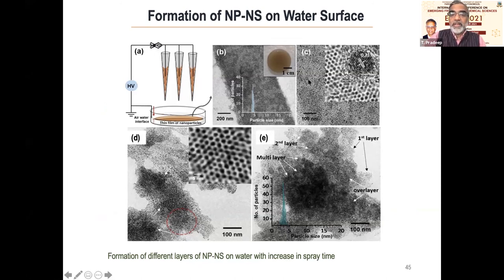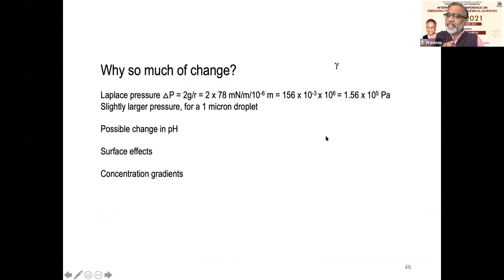So what I just told you is that very many interesting things happen. So why are they happening? One reason could be the Laplace pressure. But in a monolayer the Laplace pressure is not so high in comparison to atmospheric pressure. Here, at the scale of a few microns, Laplace pressure is a little bit higher than atmospheric pressure. There is a possible change in pH. There are surface effects. There are concentration gradients. We wanted to see, are these things really there in micro droplets?